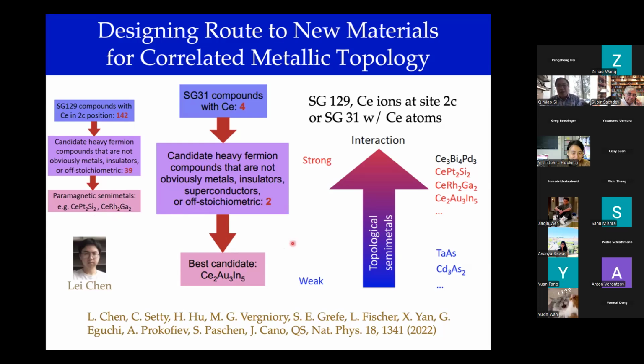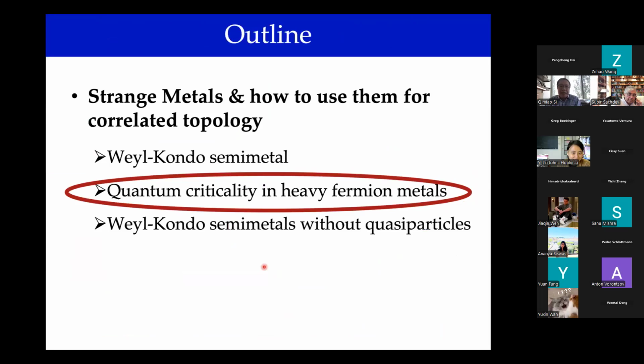It's a recipe that could be used for other space groups, such as non-symmorphic space groups; there are many other space groups, 150 plus of those in 3 dimensions, to look at. And some of these that we identify have received some experimental evidence for the existence of these nodal states. So I don't want to dwell too much upon it, but it's a cooperation between symmetry and interaction that could be put to good use even in materials discovery. So that's a brief outline of the Weyl-Kondo semi-metal work that has taken place over the past few years.